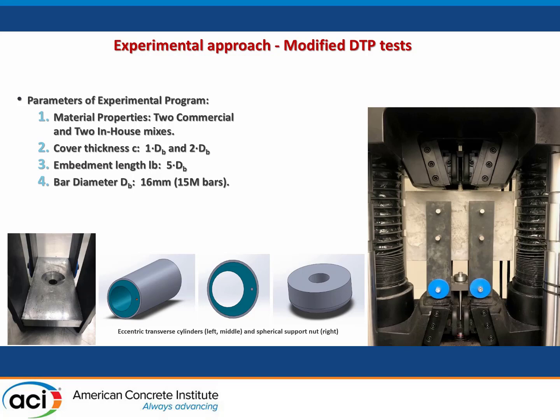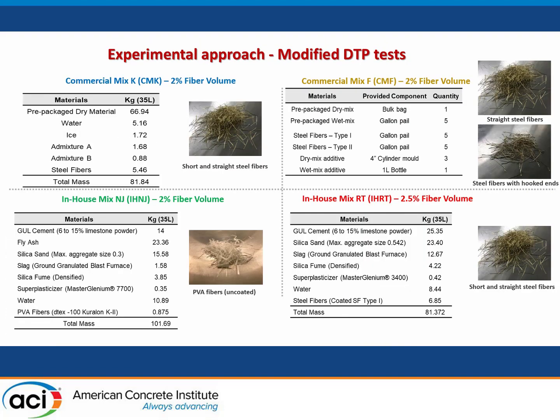The parameters of the experimental program included the following. Our parameter was the material we tested. We tested four different materials, rather three UHPC materials and one ECC material. Of those three UHPC materials, two were commercial, one was in-house made. The cover thicknesses we considered were 1D and 2D. The embedment length, as I said, was five times the bar diameter, and we only used one bar for this experimental study, a 16 millimeter diameter bar. That's the 15M bar in Canada.